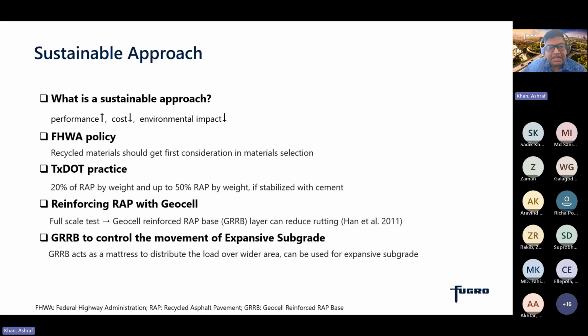So with that, what TxDOT is currently doing is, for decades, TxDOT has been trying to use more and more RAP in the base layer, and the maximum percentage they use is 20% by weight if they are blending with virgin aggregate, and up to 50% of RAP when they are stabilizing it with cement or fly ash. So they are not using 100% RAP in the pavement.